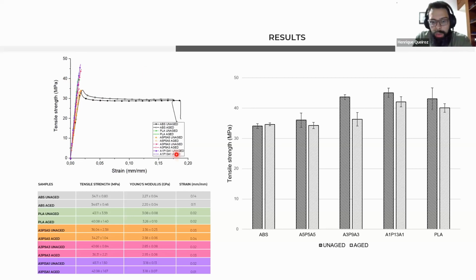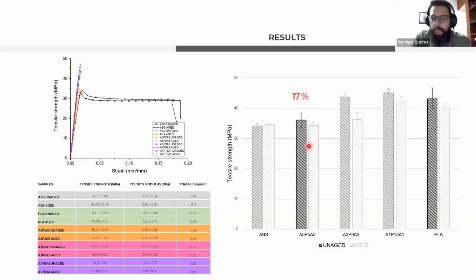Now, if we look at the tensile strength here in terms of the bar charts, what we see is that we have essentially two plateaus, right? We have the neat ABS on one side and the neat PLA on the other. Of course, the PLA is higher. And then we have a point of inflection here where one plateau becomes another, right? And there's a variation of approximately 17%. And what that means is that we found a point, this is interesting, where it doesn't matter much the number of layers of PLA. So we can go with fewer layers in terms of the sandwich structure, and it's not going to really affect the tensile strength too much, right? For the unaged case, that is.